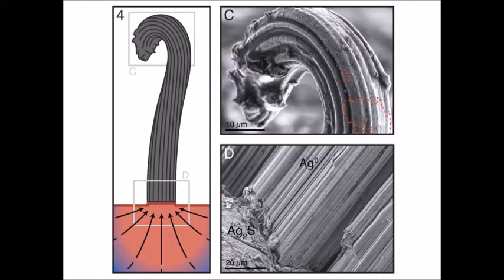And atoms are moving up from below as they are conducted through the acanthite and attached to the bottom. The wire then is translated out away from the matrix, and whatever the footprint looks like, that is the shape of the original argentite footprint, that is translated as the wire is progressively added to at the base, and that's what forms the striation morphology on the surface.